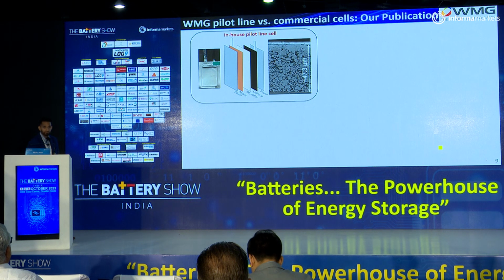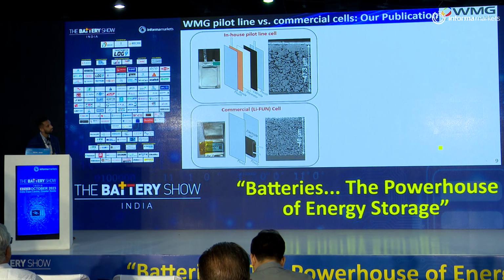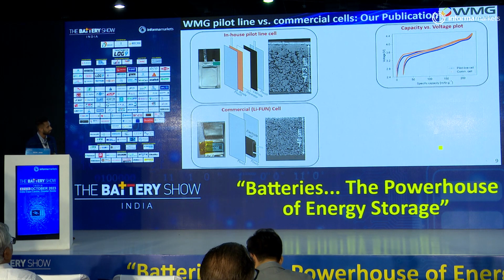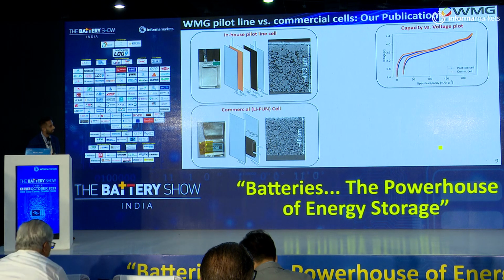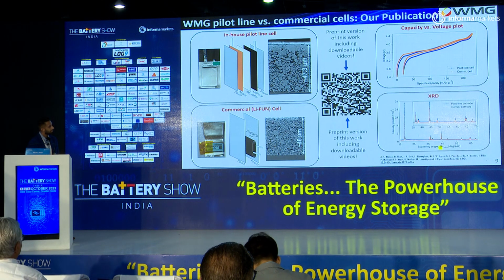Now, these are industry-relevant format cells, and we then compared these to industry-relevant Li-FUN material, which the Faraday Institution is working with very closely. We then had a look at the electrochemistry of both the cells, and they align almost identically, and the capacity fade is very similar. And we also had a look at the XRD, indicating that both the materials are atomically identical.